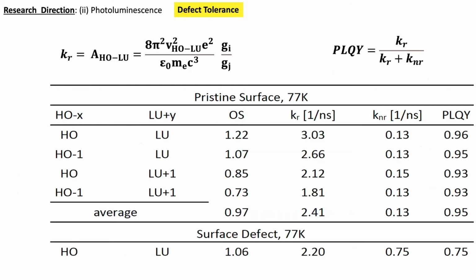And if one brings together the radiative and non-radiative lifetimes and computes this, where the non-radiative part comes from the Redfield tensor and non-adiabatic coupling, and the radiative part is just a function of the oscillator strength, like the Einstein coefficient, then it's a dimensionless quantity.